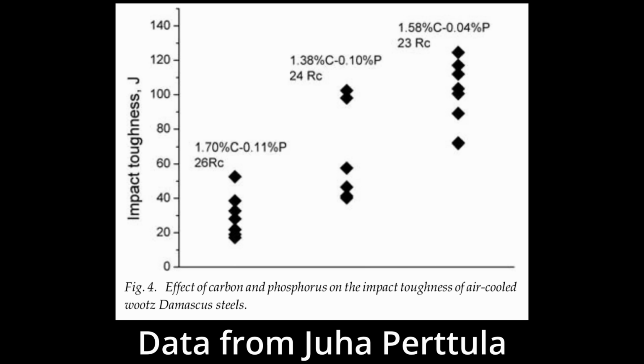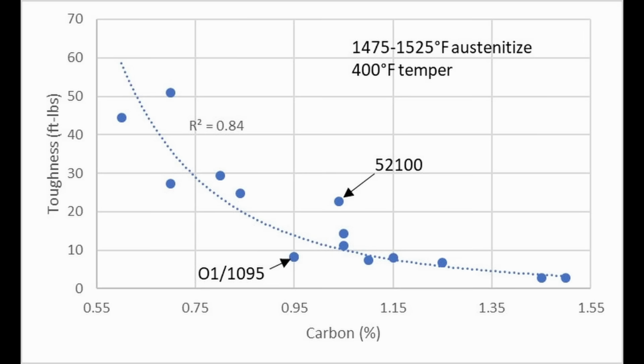So Perttula looked at the effect of phosphorus content on Wootz in a previous study because there can be relatively high contents of phosphorus in these ancient Wootz materials. And as expected, he found that the higher the phosphorus content, the lower the toughness. So that's one reason why the toughness was relatively low. Another is the very high carbon content. So in general, the higher the carbon content, the lower the toughness.